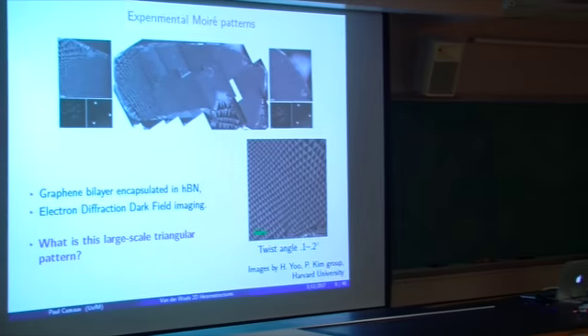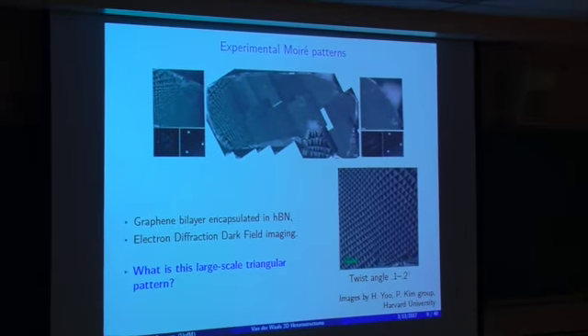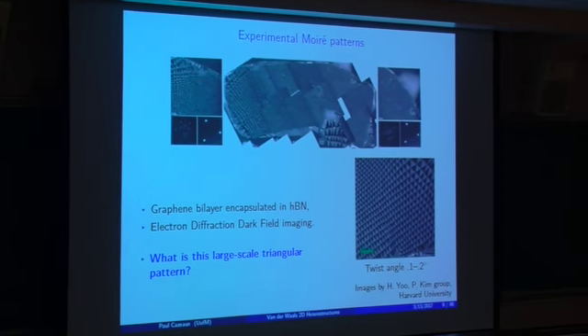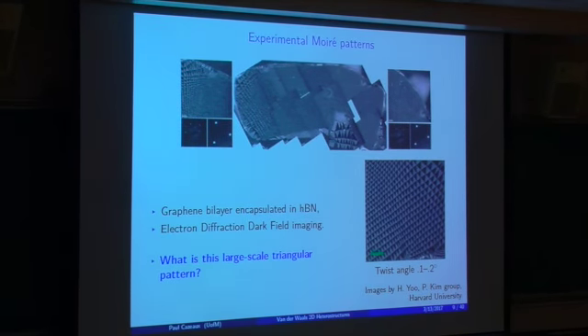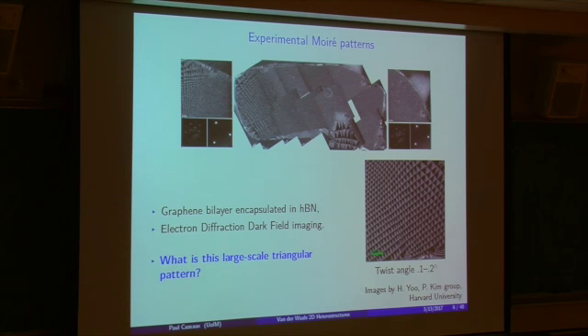But what we see is that when we look at it with just the right tools, in this case a complex method of electron diffraction coupled with some dark field imaging, then we see a pattern of domains that will appear. Domains that have a slightly different nature at a very large scale. This bar over here is 500 nanometers. It's far, far above the atomic scale. And we see that we have this kind of regular pattern that appears.